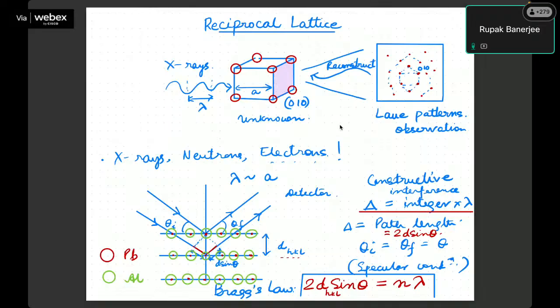You can see atoms and the planes sitting together, but it is a very local probe, which means that, for instance, if there is a heterogeneous sample, where some position is very good and some other position is not so good, then you can easily be confused about what exactly your crystal structure is. So if you want to probe nanoparticles or other things, transmission electron microscope is a wonderful technique. It's a kind of seeing and believing.